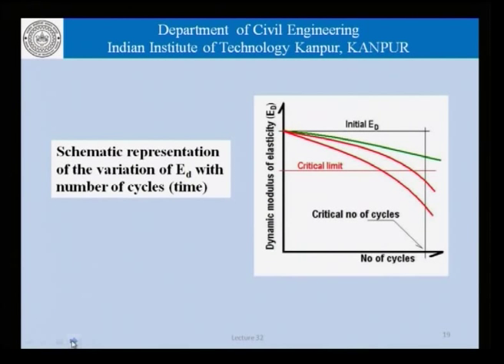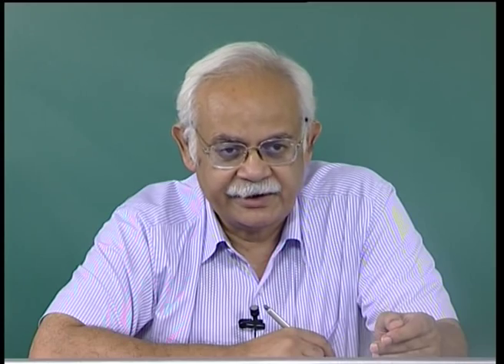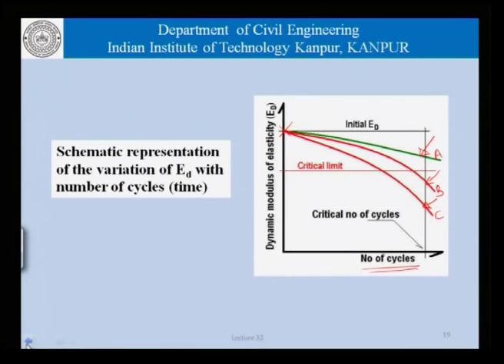values. Now, this picture here shows a schematic representation of the variation of the modulus of elasticity with the number of cycles, which is actually related to time. So, we have an initial value of the dynamic modulus of elasticity, and as the number of cycles of exposure increases, that is with the passage of time, different concretes could show different patterns of change in the E d value. So, if we have these three concretes, let us say A, B and C, we can see that the concrete A shows the minimum change in the dynamic modulus of elasticity, and this concrete C is not performing well.